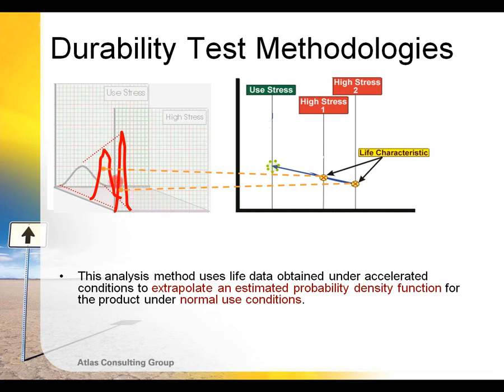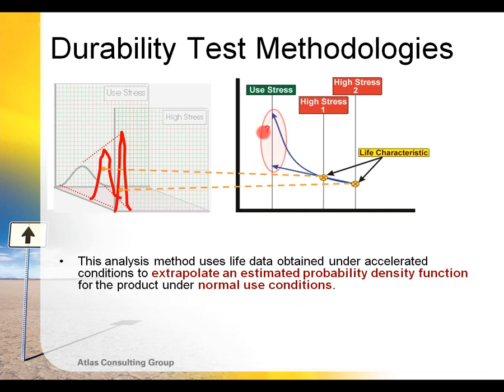And typically we need to do that at several different levels, because very often there's not a linear relationship between product performance at different stress levels. So ideally what we're trying to do is use these shorter term tests here and here to try to predict the end use service environment durability and reliability. But the reality is that we typically get a range of possibilities. So we then need to refine our tests and try to narrow down this range.